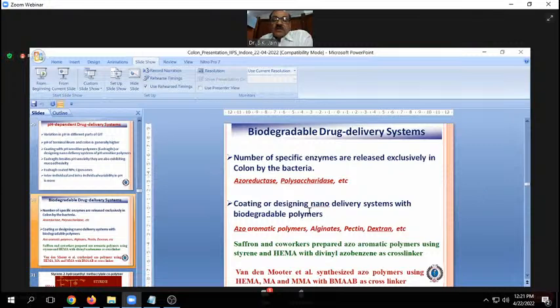Azoaromatic polymers have a number of azo bonds in their skeleton. If we fabricate any drug delivery system using this polymer, then it will not release drug in the upper part of the GIT. But when it reaches the colon, azoreductase enzyme will act on this azoaromatic polymer, right? It will cleave the azo bond, so you will have a porous skeleton and the drug will be released. Similarly, alginate, pectin, and dextran are polysaccharides, and polysaccharide enzymes will degrade these alginate, pectin, and dextran and release the drug.